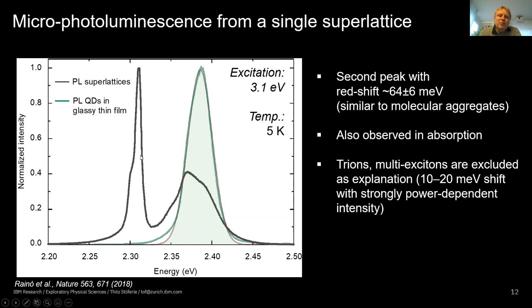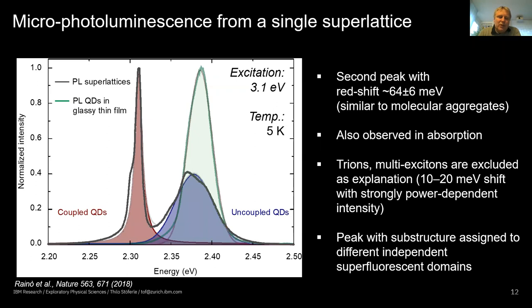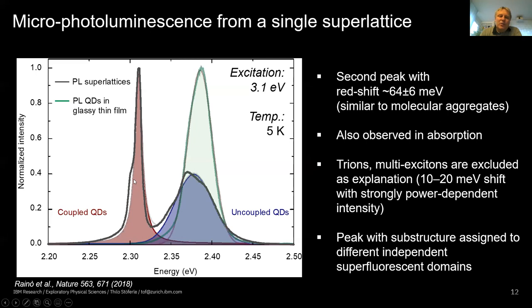This peak is also observed in absorption. Our interpretation is that the blue peak comes from uncoupled quantum dots still present, while the red-shifted peak comes from coupled quantum dots that nicely assemble and form a new state — similar to molecular aggregates like J-aggregates — causing a red shift. The substructure varies from superlattice to superlattice, which we attribute to different superfluorescent domains within one single superlattice.